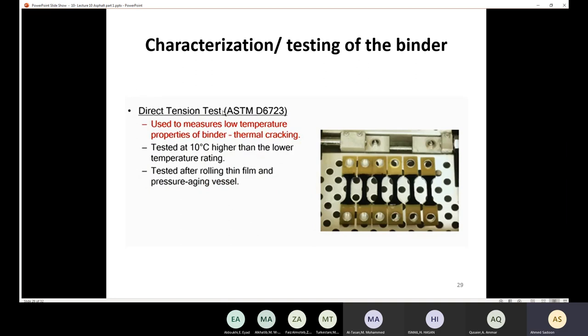We also have the Direct Tension Test. The asphalt is cast into a specimen similar to a briquette shape, at low temperature — again, 10°C higher than the lower temperature rating. This test is used to measure the thermal cracking properties of the binder. Like the bending beam rheometer, this test must be performed after the Rolling Thin Film Oven (to simulate short-term aging) and after the Pressure Aging Vessel (to simulate long-term aging).